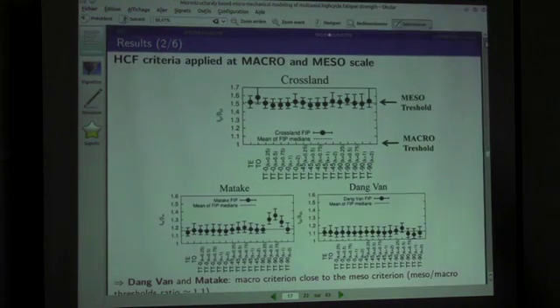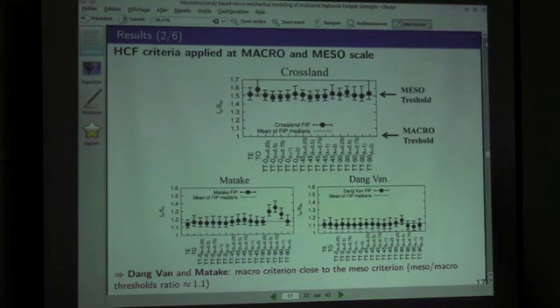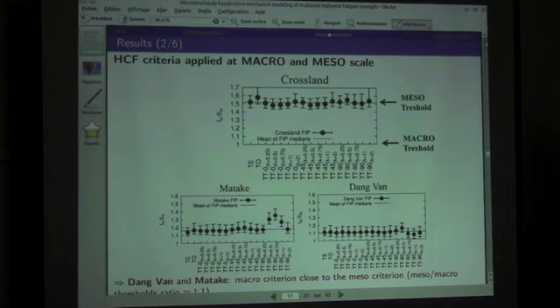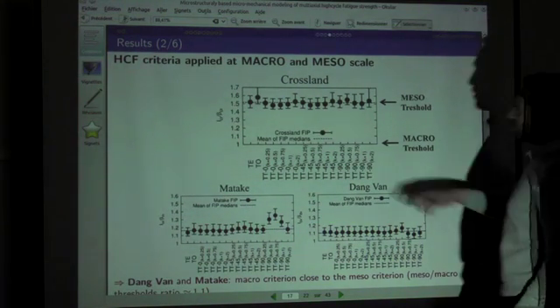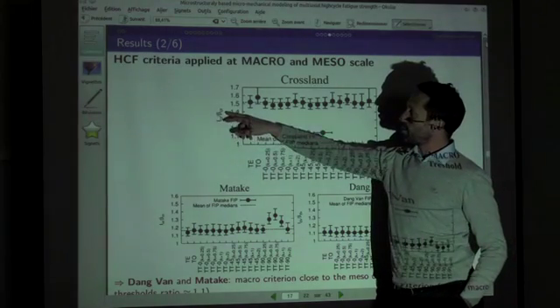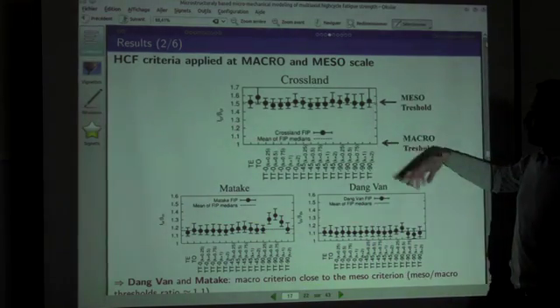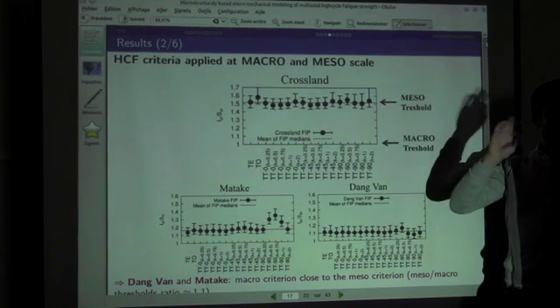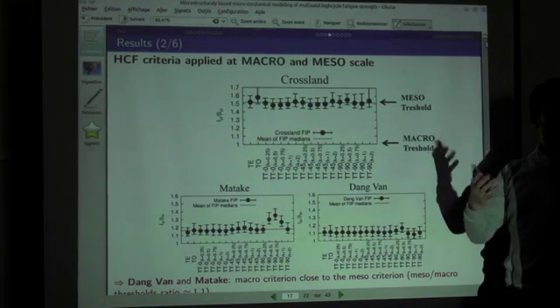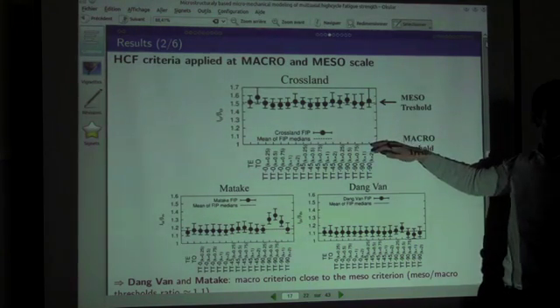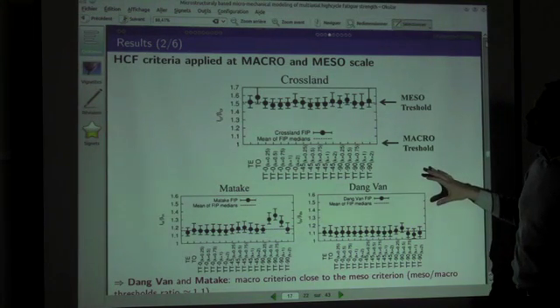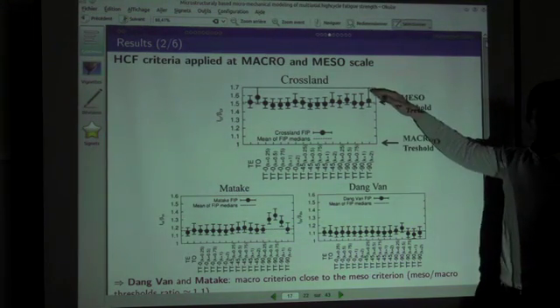So first, we analyzed the ratio between the meso threshold and the macro threshold. You have a macro one, the meso one, and you have the ratio. So if your extreme value response was the same as the macro response, you will have indicators close to 1. And depending on the parameters that you get, you have a shift between the meso one and the macro one.